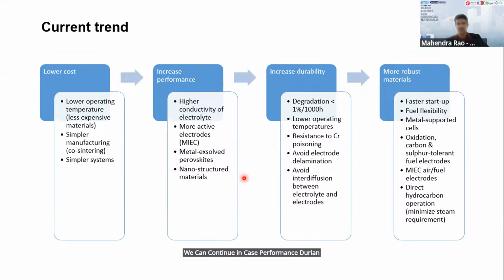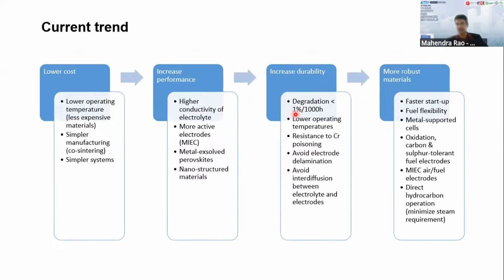The durability. So again, we know the degradation must be less than 1% per 1,000 hours of operation. I think currently the DOE target by 2026 is 0.5%, something like that. So again, the degradation is very, very critical to make sure the operation lasts between 40 to 50,000 hours, at least for the stack.